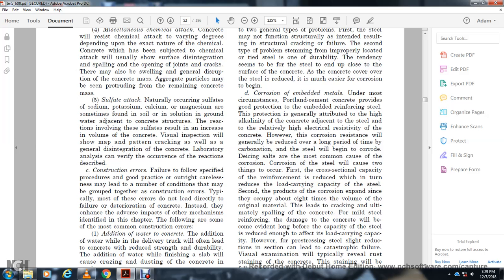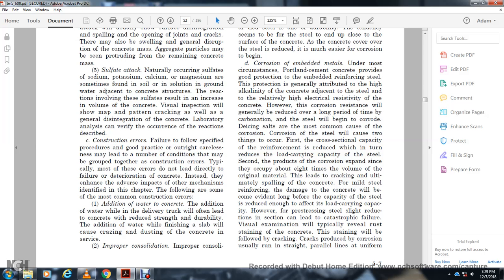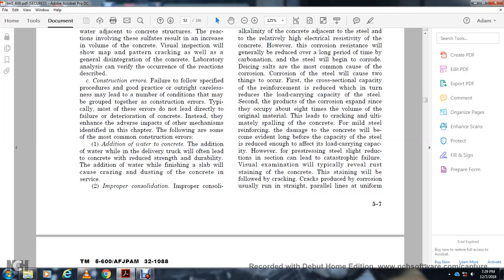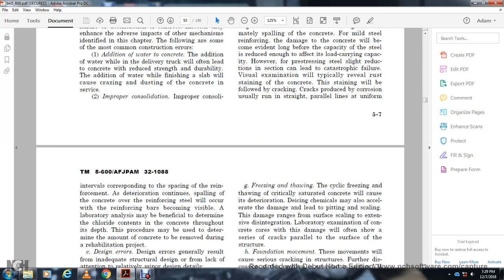Visual examination will typically reveal rust staining of the concrete. The staining will be followed by cracking produced by the corrosion, usually running in straight parallel lines at uniform intervals corresponding with the spacing of the reinforcement. The deterioration continues with the spalling of the concrete over the reinforcing steel until the reinforcing becomes visible. Laboratory analysis may be beneficial to determine the chloride content of the concrete throughout the depth of the deterioration. This can determine the amount of concrete to be removed during the rehabilitation project.